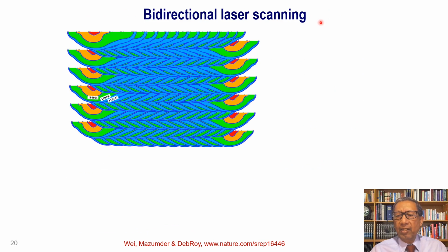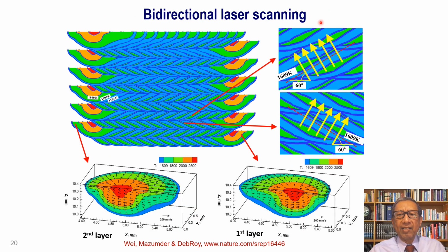Now consider a scanning pattern that alternates in progressive layers. That means in the first layer, the beam goes from left to right, and in the next layer, the scanning direction is reversed. So it goes in the opposite direction from right to left. So that is what we see here. The primary heat flow direction changes by 90 degrees. And one can see that it is perpendicular to this surface as opposed to perpendicular to that surface in the second layer. And so the heat flow directions would be very different in different layers.